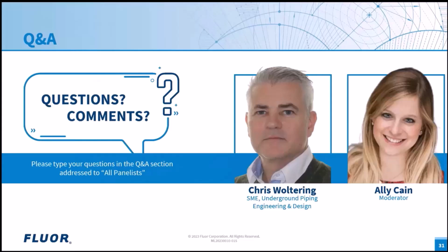Thanks, Chris. How is the GRP pipe connected to a concrete sump, and what measures are to be considered for leakages? Well, normally when a GRP pipe ends in a concrete sump, let's say for example in a sewer system, then you have several options. You can cast the pipe directly into the concrete, which means that the pipe section that is cast into the concrete is executed as a so-called puddle flange, which is there to avoid leakages during the curing of the concrete around the GRP material.